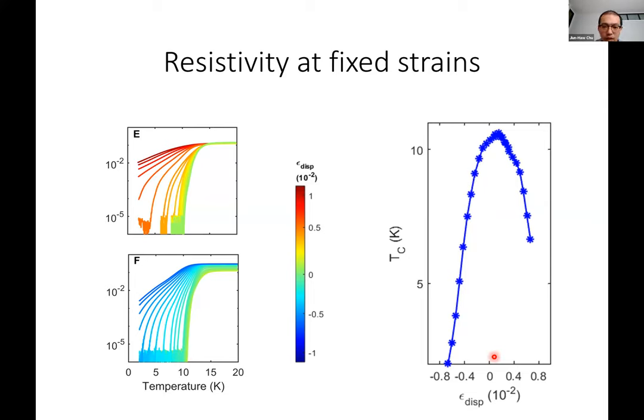So the measurement we're doing now is we're applying a constant strain and then cooling down as a function of temperature. So we're doing a vertical cut of this phase boundary. And you can already see that if there's some uncertainty in strain here, then you can have a very large uncertainty in TC, which is probably why we are observing a very, very broad transition in the RPA system.